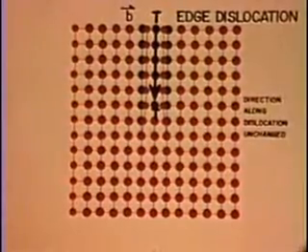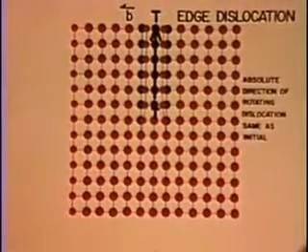At 180 degrees, it is an edge orientation with its direction downwards but its original Burgers vector. With its direction assigned upwards as for the original edge, the Burgers vector is reversed. This explains why the extra half plane is below the slipped plane as shown by the row of blue atoms. It also explains why the dislocation produces the same slip while gliding counter to the first direction.